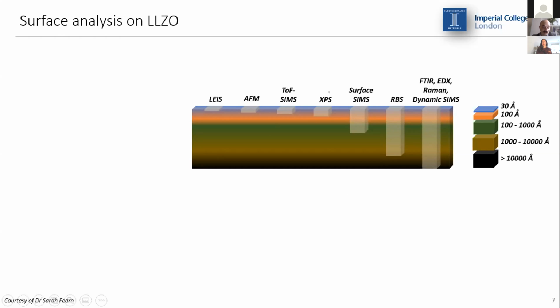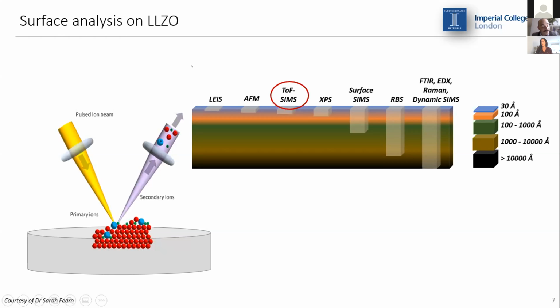In this presentation, I'm going to focus my attention mostly on XPS and TOF-SIMS. XPS is quite a common technique. However, for those of you that are not familiar with TOF-SIMS, I'm going to explain very briefly how it works. It's first of all a destructive technique. We have a primary ion beam that impacts the surface of our samples, and by doing that, we break the surface of the sample into its chemical components, which are then ionized to form secondary ions, which are encapsulated in a time-of-flight channel and detected by a detector.